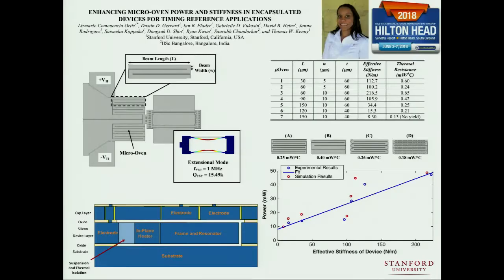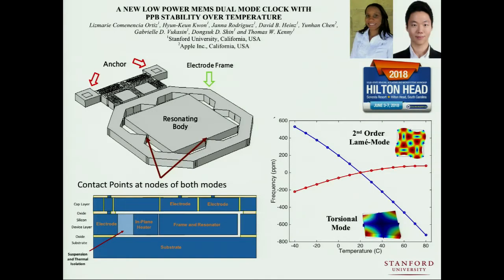So the last couple of years, and Liz Marie is sitting here, we've been looking at the optimal design of these in-plane suspensions. So we have a pair of anchors and sort of a slab of material that hangs off the side from those anchors. We've built folded suspensions that provide both thermal isolation and a place where we can build the heater. And then the tuning fork element hanging off to the right side is isothermal, and it's connected only at that one point. And we've been looking at changes in the size and shape of the suspension to try to optimize the contrast between stiffness and thermal isolation.